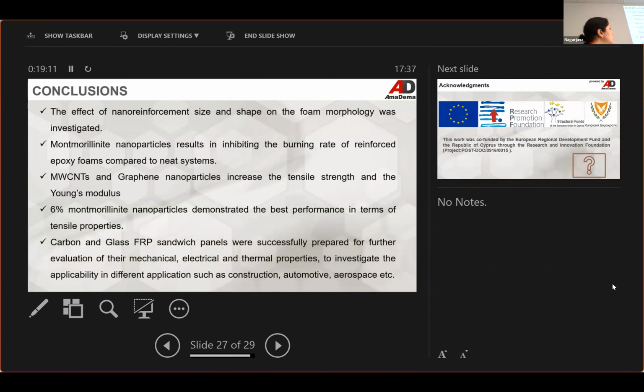Okay, and just to conclude my talk today, what we have demonstrated was that the effect of nano-reinforcement size and shape on the morphology of commercial foams has been investigated, and we've actually seen differences in the behavior when we use spherical or oblate nanoparticles. We've seen that the montmorillonite nanoparticles result in inhibiting the burning rate of the reinforced foams, meaning that this could find applications in the aerospace or automotive industry where flame resistance is desired.